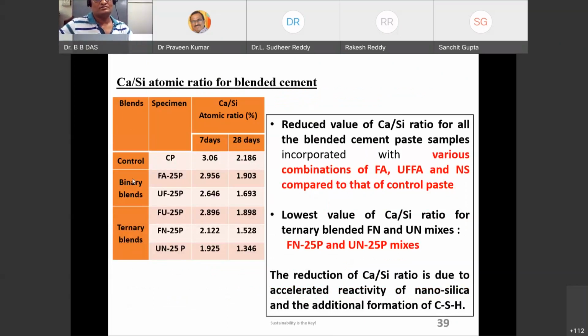Now this is a table of Ca/Si atomic ratio for blended cement. You can see this is my control, this is my binary blend, and this is my ternary blend. Let us take the example of 28 days. For ternary blends, UN-25P, it is showing 1.346. The control, which is 2.186, is quite high. That designates that this mix has more formation of calcium silicate hydrates, and that is why it is forming a dense microstructure. This is an additional validation of the conventional measurements that we did: compressive strength, density, permeable porosity, all this.